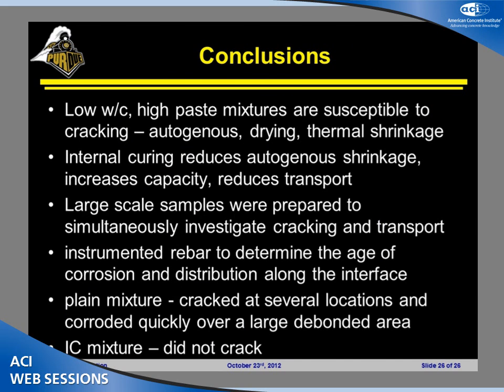Okay. So in conclusion, the whole thing has really been focused on the idea that lower water to cement ratio, high paste mixtures can be more susceptible to cracking. This is due to autogenous, drying, and thermal shrinkage. By using internal curing, it allows us to reduce the autogenous shrinkage. By reducing the autogenous shrinkage, we increase the stress capacity in the system, which means that we have a little bit more robustness when it comes to thermal cracking. We have a little bit more robustness when it comes to loading, and it may allow us to make it through that first 2 to 3 week period a little bit better.